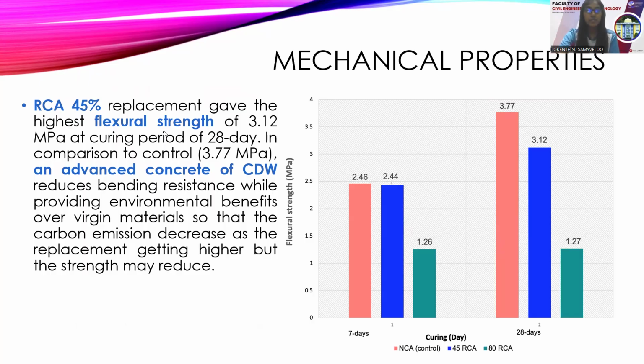RCA 45% replacement gave the highest flexural strength of 3.12 MPa at a curing period of 28 days. And this is the flexural strength graph. This is for 7 days and this is for 28 days. From here we can see the 45% and the 80%. So this is the control sample. The control sample basically gives the highest strength compared with the replacements, 3.77 MPa. So CDW aggregates in advanced concrete reduce bending resistance while providing environmental benefits over virgin material, so the carbon emission decreases as the replacement gets higher, but the strength may reduce.